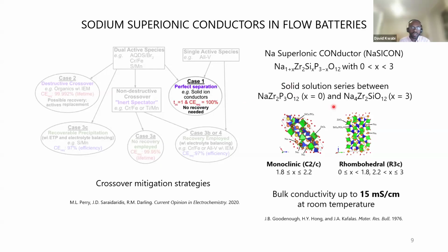We've been exploring this concept with the so-called sodium superionic conductor, or NaSICON. NaSICON is a ceramic material. It's an oxide of sodium zirconium phosphate and sodium zirconium silicate, so it's a solid solution between these two oxides, essentially. The structure of NaSICON is a three-dimensional lattice or network in which sodium can diffuse in 3D. The lattice is essentially zirconium oxide and silicon oxide octahedra and tetrahedra, respectively. Because of this 3D diffusion of sodium in the structure, we're able to get a very high conductivity. As a result, these materials are actively being studied for use in, for example, sodium metal batteries, but we believe they could be appropriate for use in flow batteries as well.